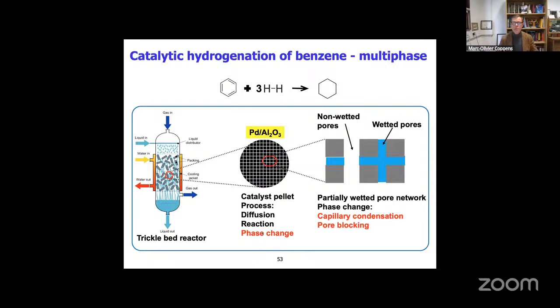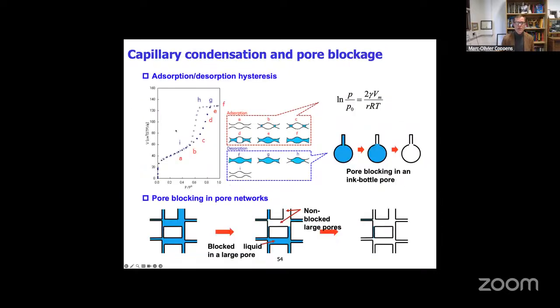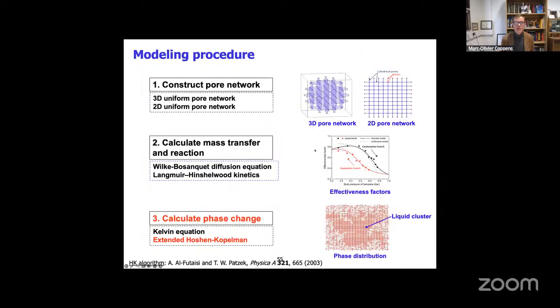To give you just one example, to finish here, catalytic hydrogenation of benzene is a multiphase process. So what I showed earlier was all gas phase or single phase situations, where things are simpler. But if you have a multiphase situation, you may cross this percolation threshold in pores, because in this reaction you will have condensation of molecules, or the pores become very narrow and you have capillary condensation in the pores. So they're only partially wetted, and you need to include these effects. I won't go into details of this, only to tell you that, and it won't surprise this adsorption community, you have hysteresis phenomena of adsorption and desorption, just like you have when you investigate materials with nitrogen adsorption and desorption. So this needs to be included in these models. But we can do that.